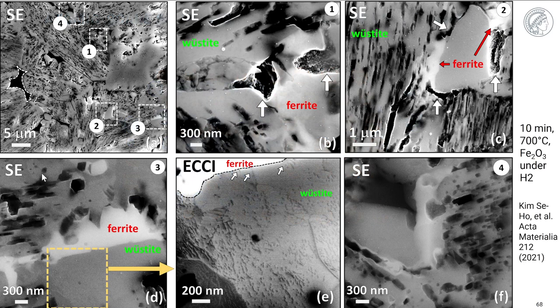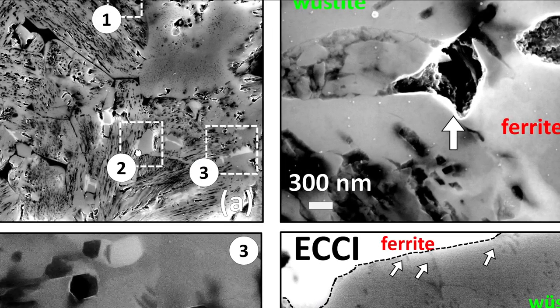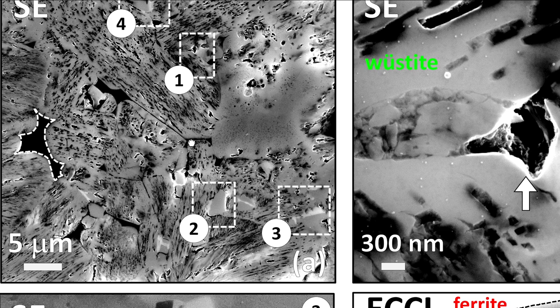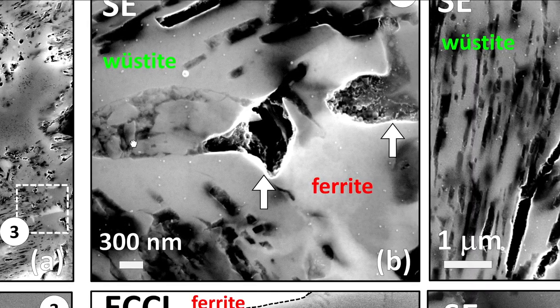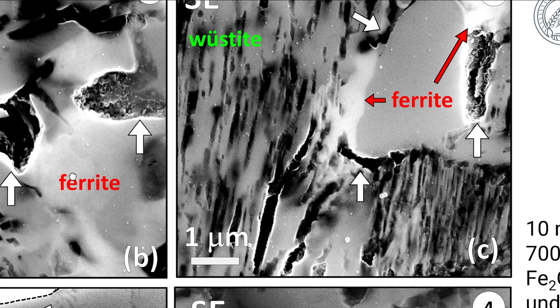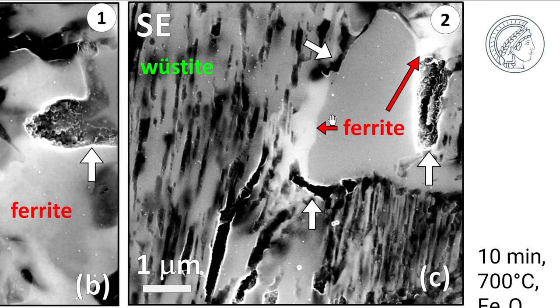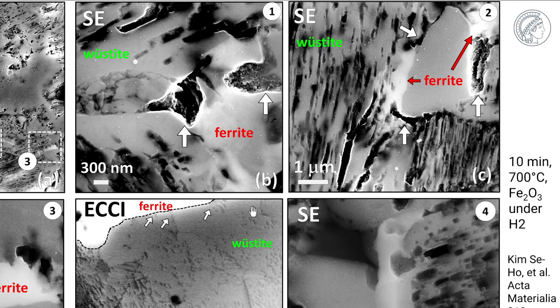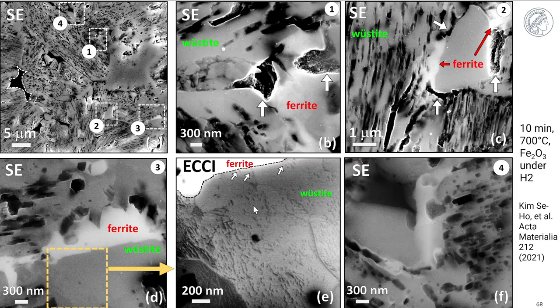However, when we really look into the microstructure, you see that things are much more complicated. There are very different microstructure features that form. For instance, the ferrite with delamination that you see here. Here's the ferrite formed on the core region of wüstite, but you also see cracks, delamination, and very complicated substructure features. These are microstructures taken after 10 minutes at 700 degrees centigrade under hydrogen atmosphere.